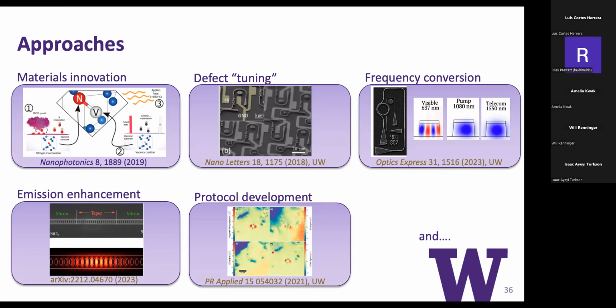Okay. And do you tend to get any straggle in the implantation? So we implant at 7 degrees, which is supposed to help minimize the straggle for ion channeling, but we don't have a way to detect whether we get straggle or not. So in our studies, we typically look at a large number. If we just see a few that are amazing, that could be a straggle ion. So we're looking typically for high numbers so we can avoid that. And of course, the big straggle ones won't couple to our optical devices for integration. Okay, thank you. Welcome.